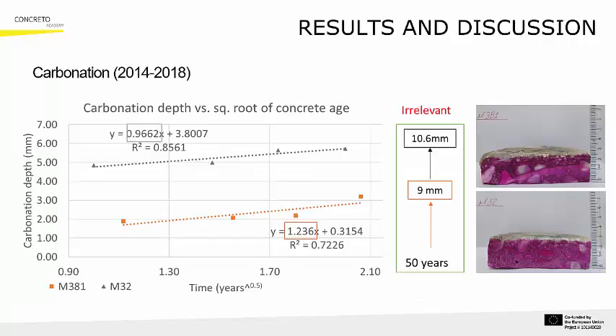Let's dive into some of the results, starting with carbonation. The graph shows carbonation depth versus the square root of time for both mixes. As can be observed, the values for OPC are almost double those for LC3, clearly demonstrating how the finer pore structure limits CO2 penetration.